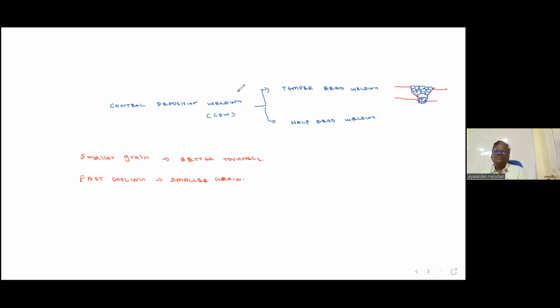Now another one is, suppose you cannot make a thin pass. Suppose your pass is thick, then when we weld over the pass, it will not heat entirely. Then we have to remove half of the pass. You have to grind it and make it a thin pass. So suppose this is my other example. I am making a root pass. Now if the thickness is thick like this and you think it will not heat, we have to grind it and remove half of the pass. That is called half bead welding. Only half the bead we are removing. So every pass when you make a weld, you have to cut it off.